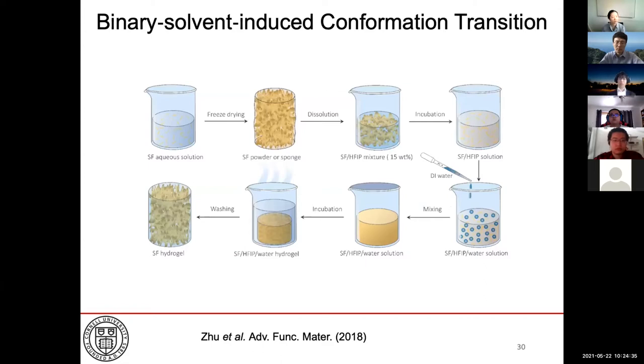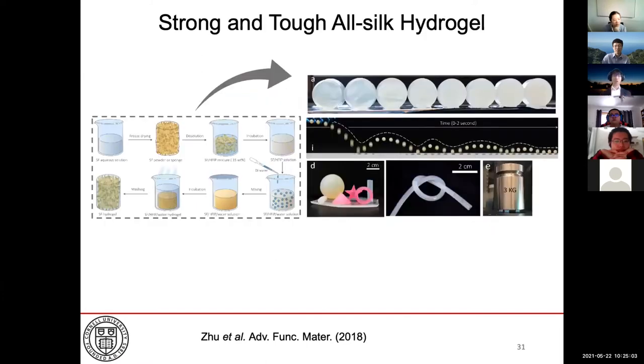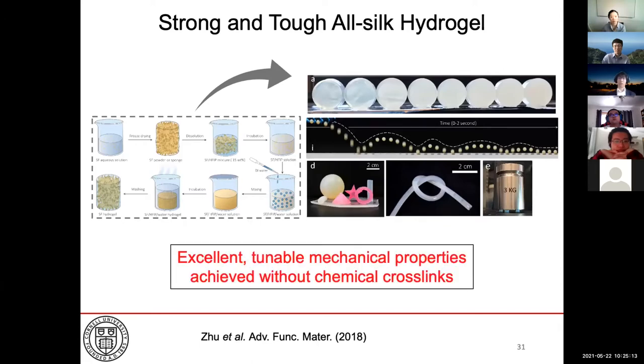And such a scheme was actually realized experimentally by my collaborators, and we termed this the binary solvent-induced conformation transition. And the top half of this procedure over here should be a fairly standard protocol to those who are familiar with it, where silk is degummed, dissolved, dialyzed, freeze-dried, and redissolved in HFIP. And the bottom half is where the gelation occurs by dripping deionized water into the solution, and upon incubation and washing, we actually obtained strong and tough all-silk hydrogels with variable optical properties depending on their processing conditions, and they are mechanically robust and deformable, and therefore we actually achieve excellent tunable mechanical properties without any form of chemical cross-linking.